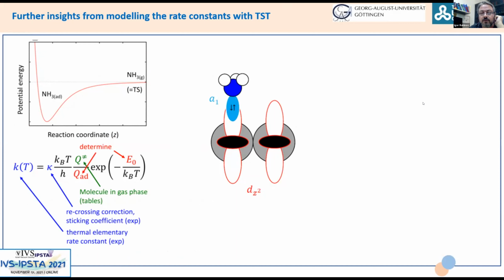And then the prefactor is sensitive to the type of interaction the molecule experiences, because what we have in this expression is, of course, the recrossing factor to correct for crossing back through the transition state plane. And this we know because we know the sticking coefficient from the experiment. We can put the transition state, because this is a barrierless adsorption, actually, here, and then the partition function for the transition state is simply the partition function of the gas phase. And then the partition function of the adsorbate becomes extremely sensitive to the kind of interaction.